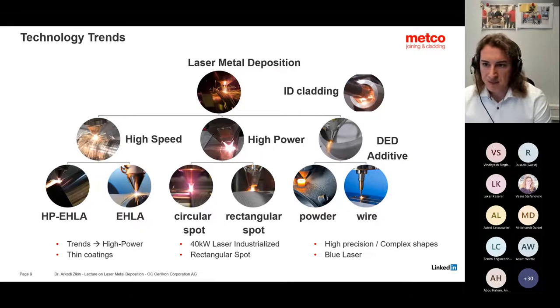On the other side, I would say six, seven years ago, the technology EHLA, which is a German abbreviation, translating to extreme high-speed laser cladding, has taken more and more attention, also developing in the direction of high power nowadays. But an important difference here, which I will introduce in the next slides, is that we produce primarily thin coatings. In this case, I mean something between 100 to 250 microns per pass, but with extremely high surface coverage rates, which go in the direction of 5 square meters per hour or even more.